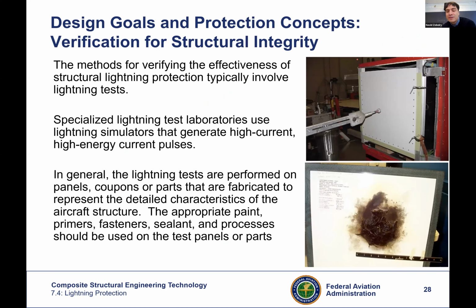So this is the type of test that I could find online, at least. It's a composite plate, and you will integrate your design on top of that. So the paints, the foil to dissipate the energy, anything that you want to design, the fasteners is integrated into this. And then this rod basically creates a lightning strike on the surface. You will measure the amount of energy that goes into it. You will measure the amount of damage. You will measure if there are any sparks, and then that will be the outcome of the test.